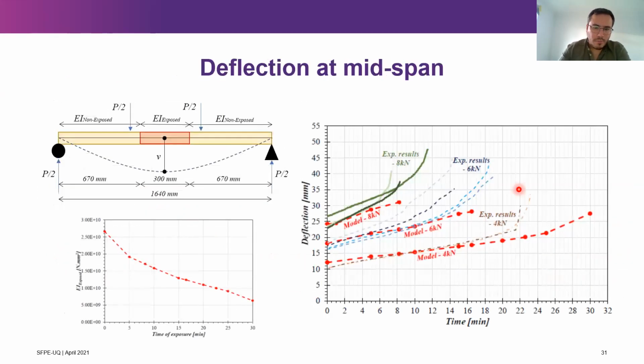So we also propose a model to calculate the deflection. So you see, this is the deflection against time of exposure, right? Here are the results for 8 kilonewton. Here you have the results for 6 kilonewton, and here for 4 kilonewton, where the material behaves quite elastic, it's quite good. But when we are very close to the failure, then we have more difference between our model and our experimental results. But again, the concept was very simple. You had a part of your beam that was changing properties because of the effect of temperature. We managed to predict the reduction in the stiffness, and with the reduction in the stiffness, we were able to calculate the deflections.